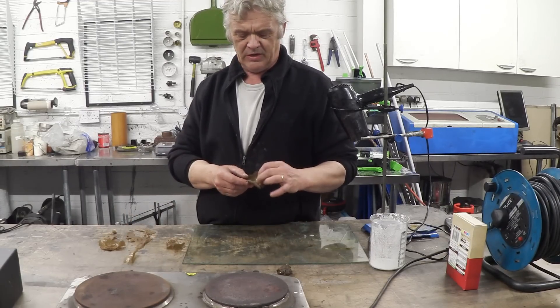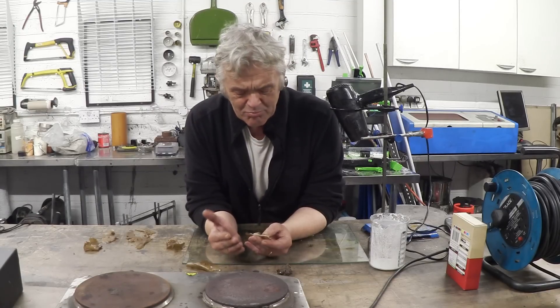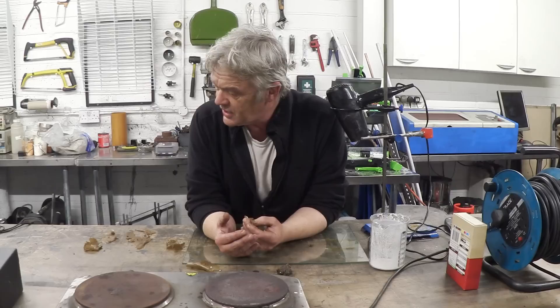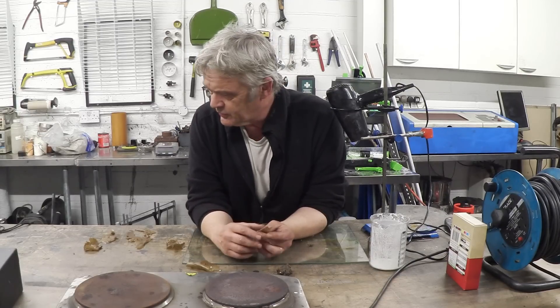I made a chunky block by rolling up most of the film, and I kept some of the film — so here's our seaweed plastic film, with various bits lying around. It is quite brittle like this. The part of the seaweed that makes it slimy acts as a bit of a plasticizer, but you're never quite sure how much you've got, so you can add a bit of glycerin. Two tablespoons of glycerin added to the mix would make it much more flexible and not as brittle.